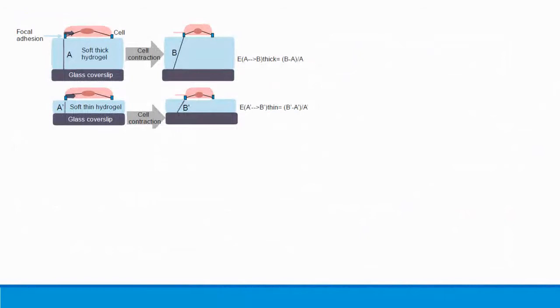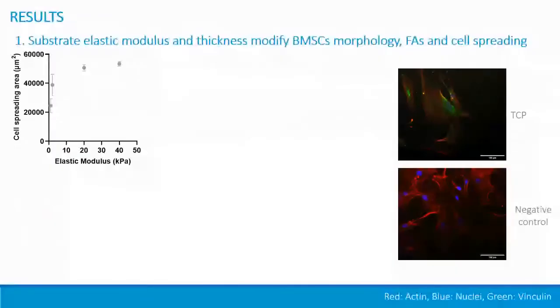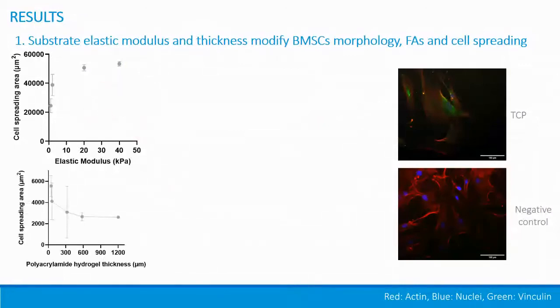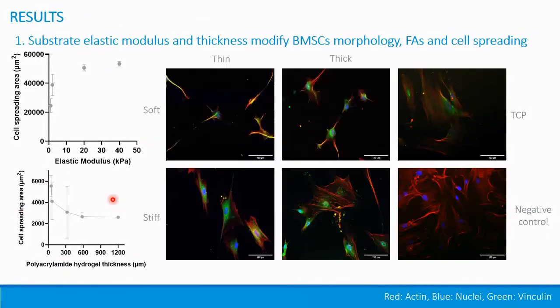We found that bone marrow stromal cells are sensitive to mechanical changes, as they spread more on stiffer substrates and on soft gels when decreasing the thickness. Also, the cell morphology was modified. Actin stress fibers can be clearly seen on cells on stiff substrates, regardless of the thickness, while cells on soft substrates don't have these clear fibers and focal adhesions. However, the thickness modified the length of the cells.